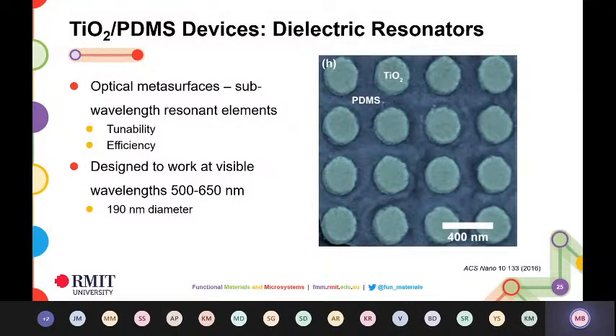So trying to make these meta surfaces is quite nice because usually meta surfaces were made using metal. Now metal is a highly lossy material, so it's not really efficient to use it for meta surface applications sometimes. And the fact that it's on PDMS also lends the tunability. So the fact that you can now stretch it and tune the meta-surfaces is an interesting application for the entire concept. So they designed these to actually work in the visible wavelengths.